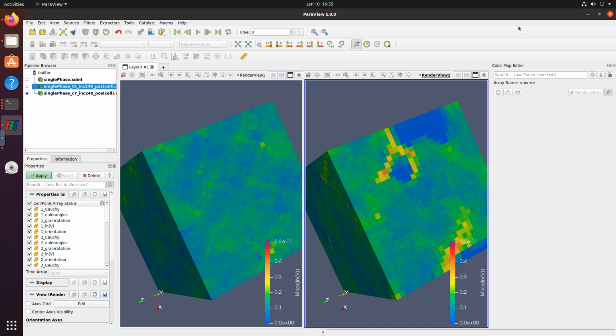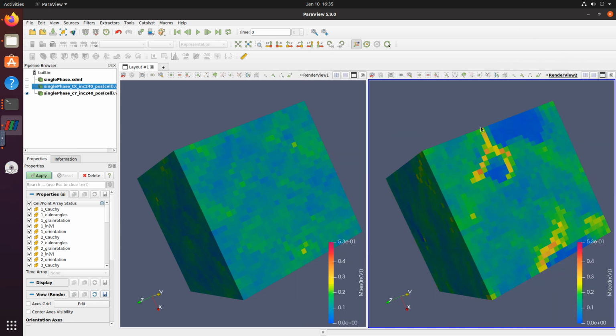And also we looked at the global results. We can also, for example, just use any plotting software, Excel, MATLAB, Matplotlib, Python libraries, or whatever, to compare the overall stress strain curves, and we will see that there will be significantly higher hardening in case of dual phase steel as compared to single phase steel, right? So yeah, this is generally what we wanted to cover today.